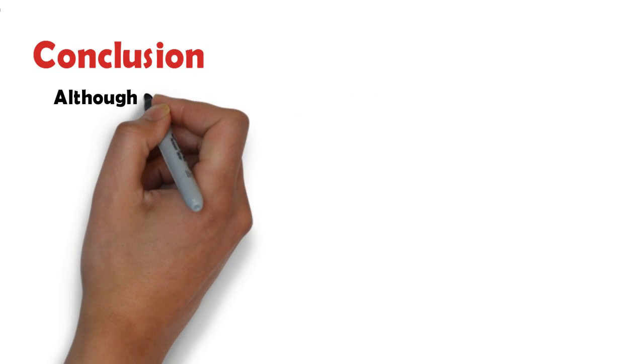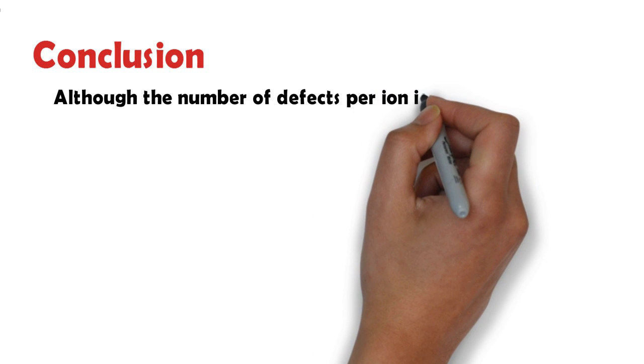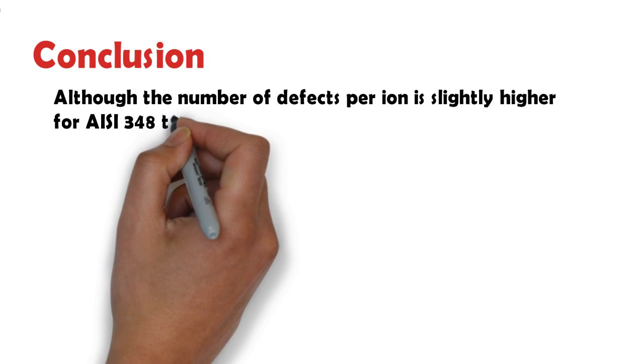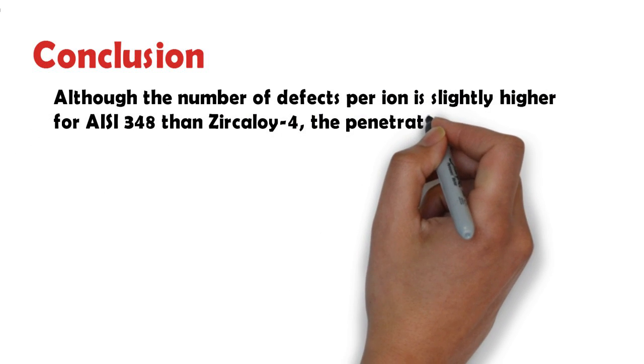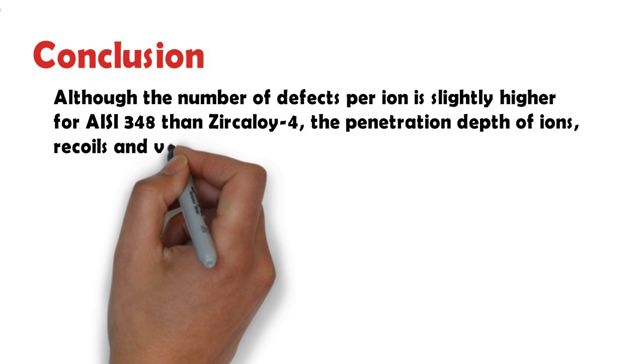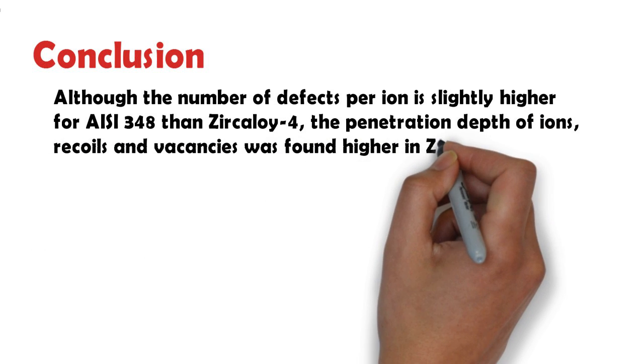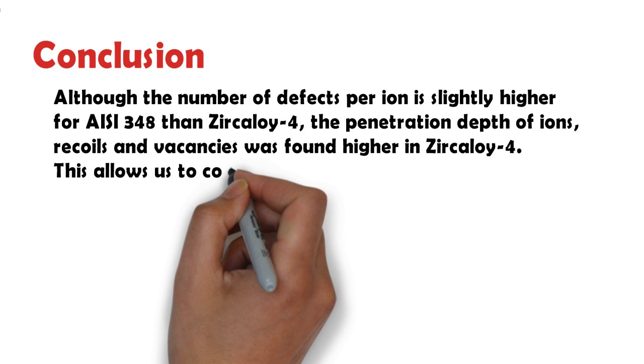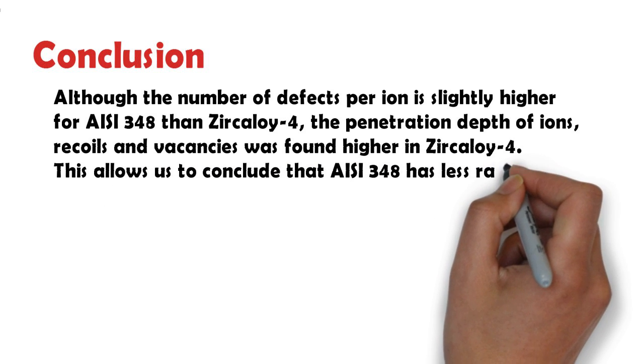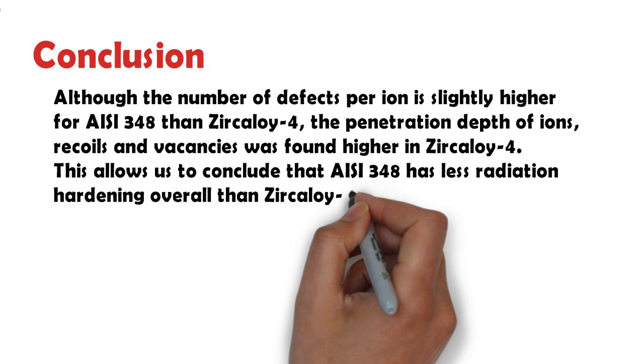Although the number of defects per ion is slightly higher for austenitic stainless steel 348 than zircaloy 4, the penetration depths of ions, recoils, and vacancies were found to be higher in zircaloy 4. This allows us to conclude that austenitic stainless steel 348 has less radiation hardening overall than zircaloy 4.